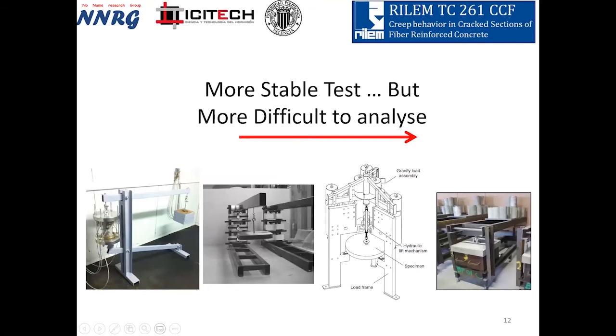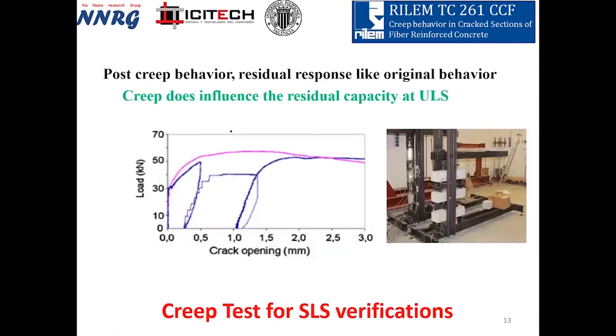Well, it is clear that if we want to understand the material, the clearest and simplest methodology is the direct tension load, but it's very difficult because it's not a stable test. If we are thinking in creep, we need to think in a 1 year or long-term test. Then this is difficult to do, but if you go in the opposite direction, toward plates, the problem is to understand what happens in this test. Then the easier the test, the more difficult it is to understand the result.